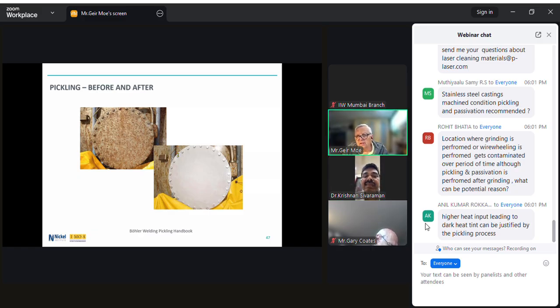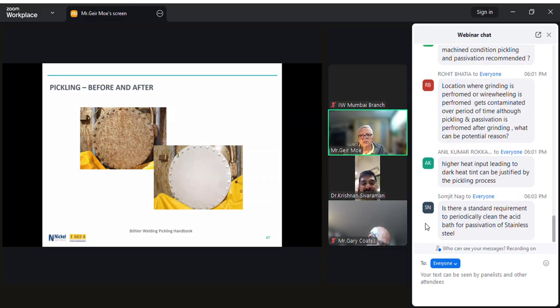Well, with the Inconel, we're talking about a nickel alloy again. As I said, nickel alloys are generally very resistant to hydrochloric acid, so they're very resistant to pitting by chlorides. But generally, you would be doing it for cosmetic reasons, because your customer is generally not going to be happy if he sees iron contamination rusting on the surface. So typically you would do some type of a passivation treatment. A lot of times this is something that's best to discuss with your customer.